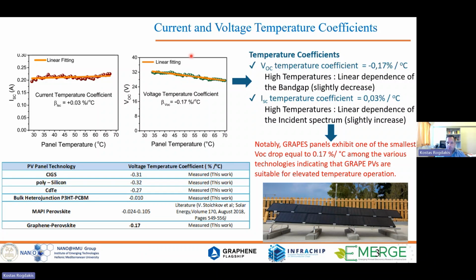It was very important to identify that this perovskite technology has a very low negative, but very low, VOC thermal coefficient. This is the open circuit voltage thermal coefficient that is very low. It's lower than silicon. That indicates that this technology is affected less at high temperatures compared to silicon. So for some applications, it's better than silicon.